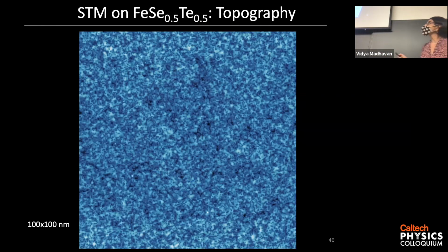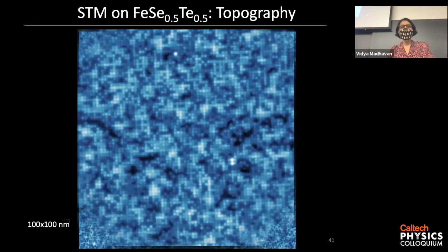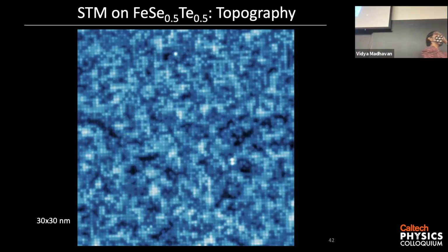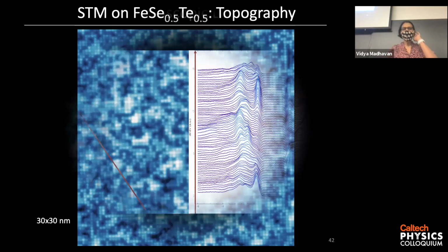And first, if you look carefully, you might be able to see the dots that are the atoms, but we can zoom in. And now you see the dots clearly. Some of them are selenium and some of them are tellurium. So you can see all the inhomogeneity here. That comes from the fact that you have 2 chemical species. But you see the nice square lattice formed by these atoms.